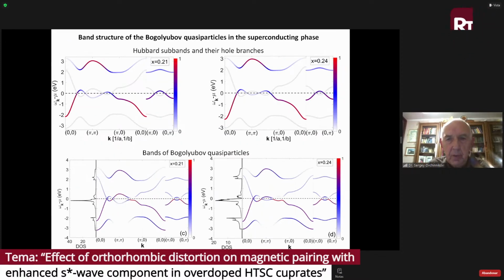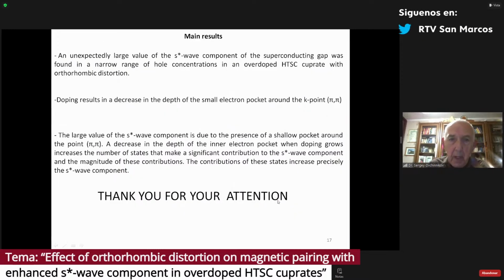And this is the structure of the Bogoliubov quasi-particles shown here, and the density of states. Of course, the density of states has a maximum near the flat band, near the pi-0 point. The same for overdoped, a very sharp peak in the density of states due to this flat band. Well, so I'm close to conclusion.